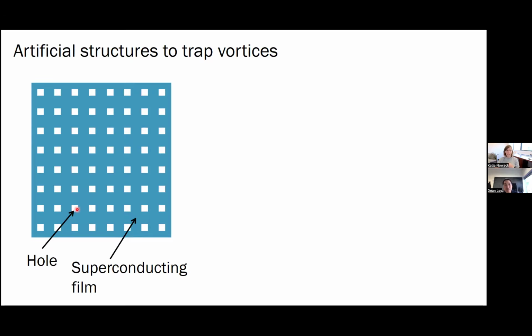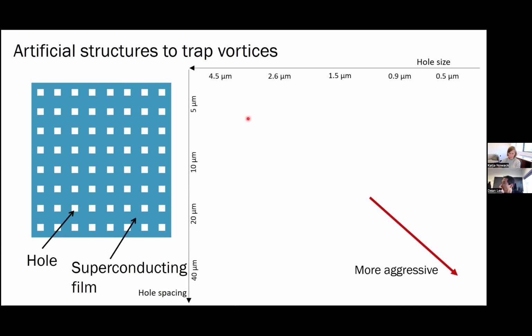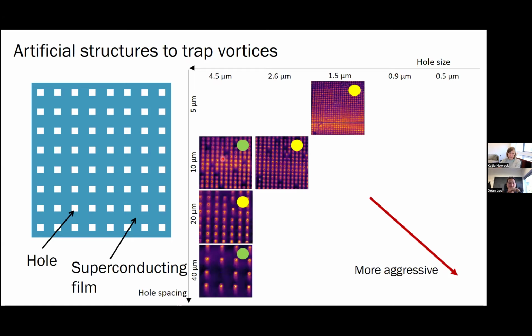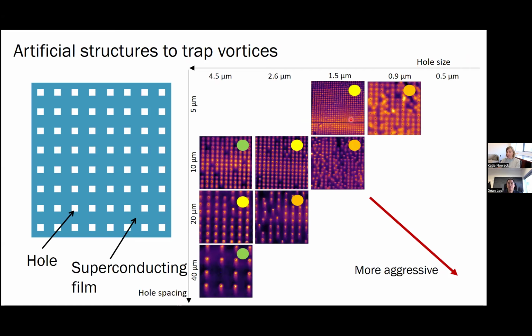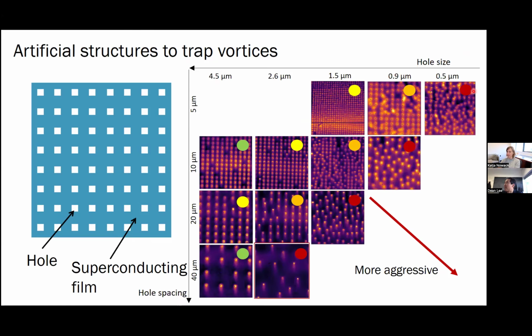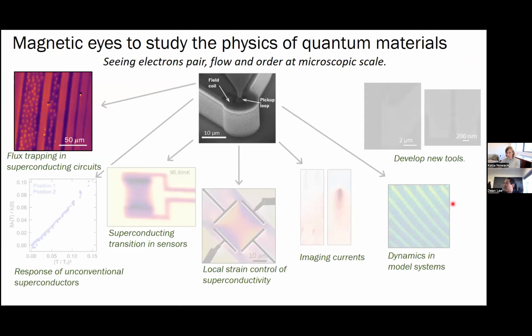And so the kind of work that we do is answering questions like, how big a hole do I have to make, and how closely do they need to be spaced, so that these artificial structures successfully trap all the spontaneously forming vortices that you might have in your film. These are images that we can take. Here I show images of these artificial structures where on this axis, the spacing between the holes varies, and along this axis, the holes get bigger. We can see that at a certain combination of spacing and hole size, things work fine. Green means great, it worked. Whereas if the holes get smaller or more spaced out, these artificial trapping structures actually stop working. Okay, so that's one kind of project that we do.